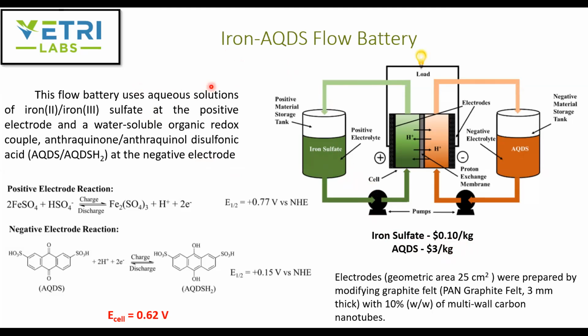So this iron-AQDS flow battery uses an aqueous solution of iron 2+ or iron 3+ sulfate at the positive electrode, and a water-soluble organic redox couple like anthraquinone or anthraquinol disulfonic acid at the negative electrode. Basically, the positive electrode is based on the interconversion of iron 2+ and iron 3+, and at the negative electrode, the AQDS undergoes redox interconversion between the quinone and the hydroquinone forms, and you have protons getting released. As the source of protons, they have mixed both reservoirs with 2 molar sulfuric acid, and on the positive side, the high concentration of 2 molar sulfuric acid ensures that the complexes of iron do not hydrolyze. The protons also serve to transport the ionic current across the cell.